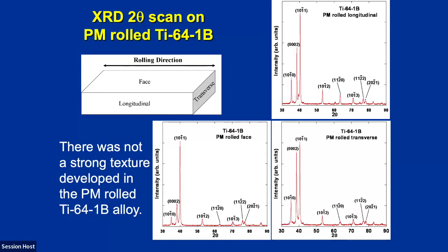So if we look at this texture, we can look at it in a few ways, from EBSD or from X-ray diffraction. And this is the PM rolled in the longitudinal direction, and the transverse in the rolled face. And we didn't see a very strong texture develop in this material. If you look at the extruded, though, the alpha phase was strongly textured, and we already see the morphology of the titanium boride whiskers.